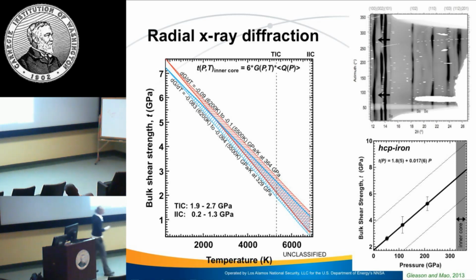Now at high temperature, we can do an extrapolation. We can estimate what the effect of temperature will be. It takes the strength down to 1 or 2 GPa. That's really weak. Okay, so could that low strength possibly encourage different kinds of dislocation flow or solid state flow inside the innermost inner core that then sets up this anisotropy? Perhaps. But best would be to make a simultaneous high pressure, high temperature measurement and look at strength.